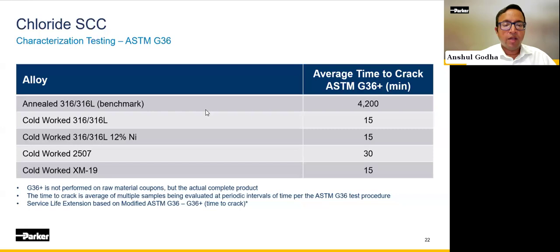So we have done some of that modified ASTM G36 testing in our labs. And in this slide, we are trying to show the trends between the different alloys. What is very noticeable is if you are dealing with an annealed material, such as even annealed 316, the average time that it takes for the part to develop a crack is quite high. Compared to that, for cold worked alloys, irrespective of which alloy we choose, we see a dramatic reduction in that time to cracking. Of course, the higher alloyed alloys do slightly better.